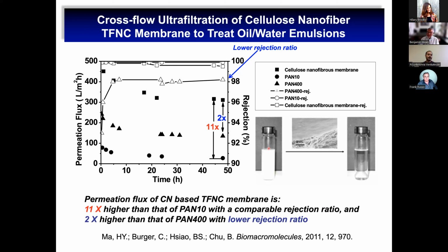This is an oil and water emulsion. With this membrane, we can completely remove the emulsified oil droplets, since the surface coating is nanocellulose. So they're very, very hydrophilic.